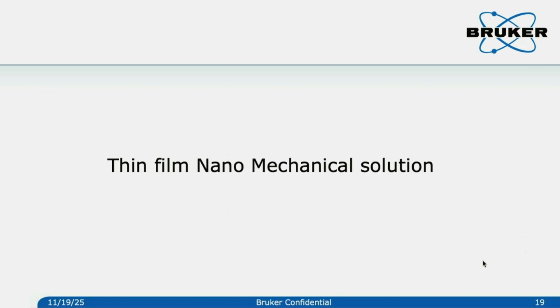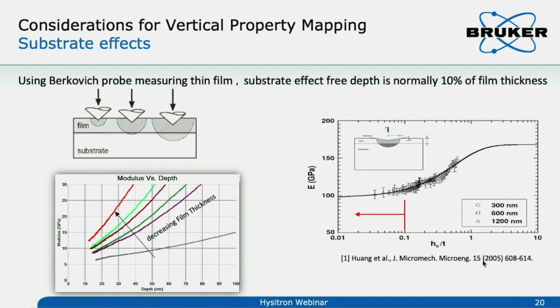Secondly, I would like to talk about thin film measurement. For thin film measurement, we know we have a challenge we call the substrate effect. This is the contact depth of the nanoindentation. This is a thin film sample. When you go deeper and deeper, your stress will penetrate over the interface, and your substrate starts to deform. So that will influence our hardness and modulus data. We call it the substrate effect. Typically, if we look at the papers, at almost 10% of the film thickness, you start seeing the substrate effect.